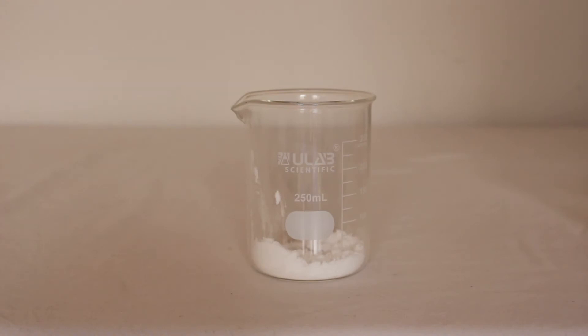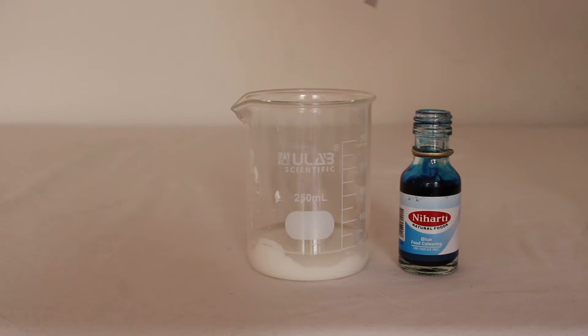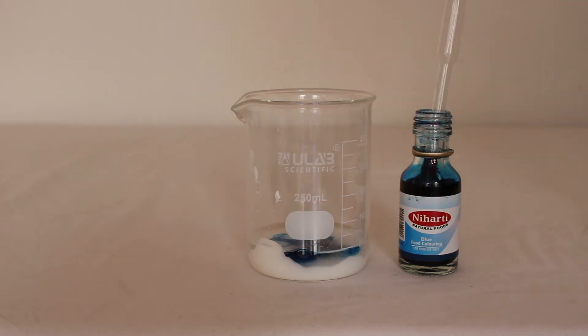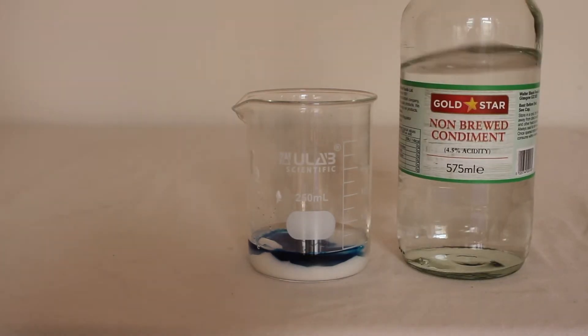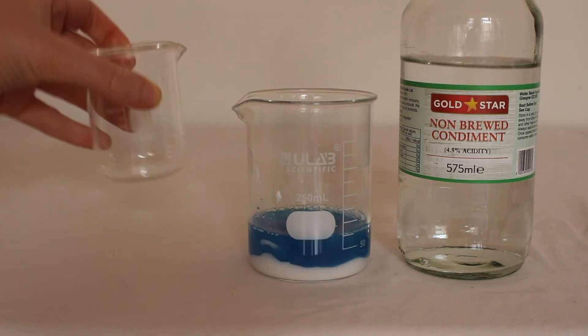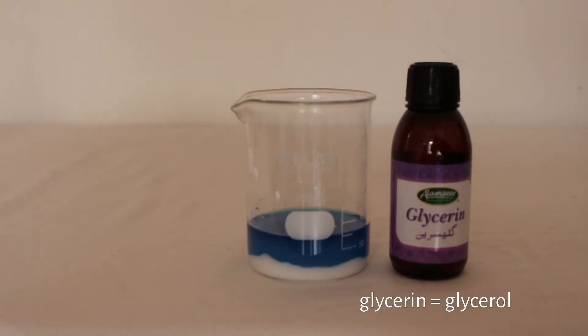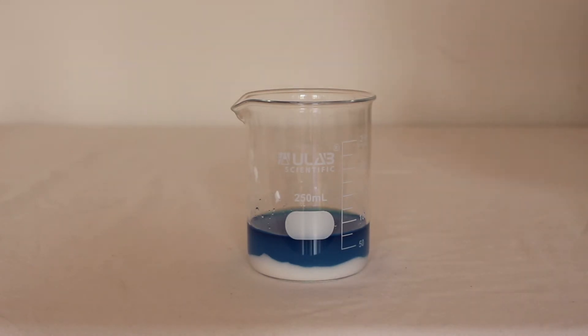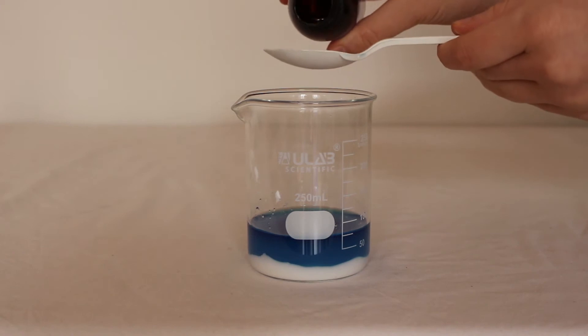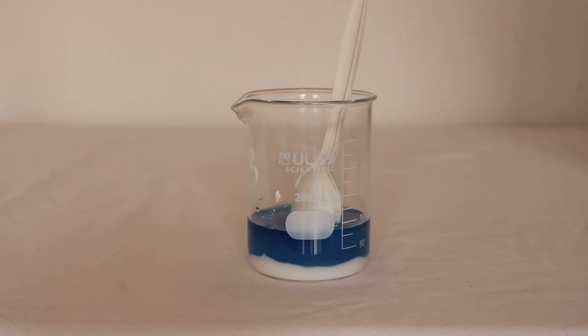To this starch, I'm going to add some water and some blue food colouring. I'm going to add an acid to this mixture. The acid I'm going to add is acetic acid, also known as vinegar. So I'm going to add 30 millilitres of that. Finally, I'm going to add some glycerol. Glycerol is a pretty common chemical which is found as a sweetener and also in soap. We're going to use this as a plasticiser, which basically means it's going to help our final product stay kind of rubbery and not break apart. We're going to add 15 millilitres of the glycerol.